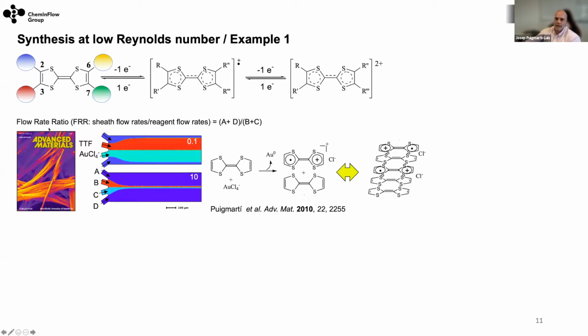It's very important, and I want you to pay attention here, because this is a terminology that will appear later on in the presentation, and it's about the flow rate ratio. I define the flow rate ratio as the ratio of the sheath flows versus the reagent flows. What you see in this condition here is that the flow rates of these two reagents are very high, higher than the sheath flows. This is why you have a very low flow rate ratio. But when you have very high sheath flows, then what happens is that you confine the reaction area. So as you can see, playing with the flow rate ratio, you can define the time that you want these two reagents to react, but also the space where you allow them to react, right?